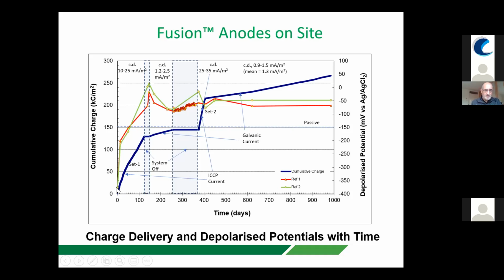And we can see that we started from a very negative potential. The steel was actually corroding at the beginning, but very quickly the potential had become very passive, even within this 120 kilocoulombs. We stopped at 120 or thereabout because that's what we found in the lab. We were able to stop corrosion at 2% chloride. We could see quite clearly that we passivated the steel considerably. Potentials have almost become positive.